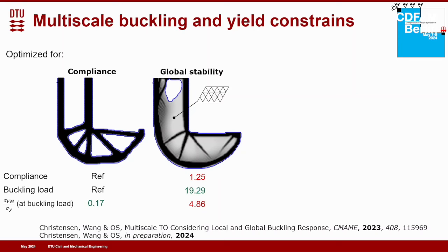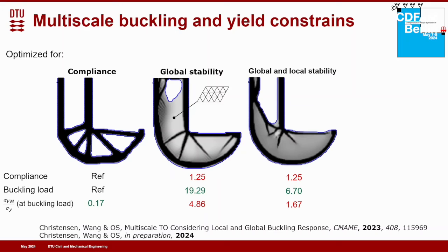The problem here is also that in these light gray regions, we have very low density of thin struts. So if we actually optimize also to prevent local buckling, then we get this structure. And what you see here now is that we don't have any low density regions anymore. We have fairly high density regions because we want to avoid the local buckling. So now we still have 25% decrease in stiffness, but we still gained a factor of almost 7 in buckling, both local and global, but the structure will yield plastically before it buckles.